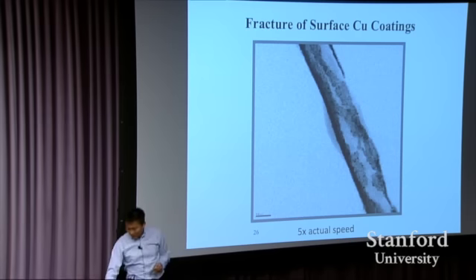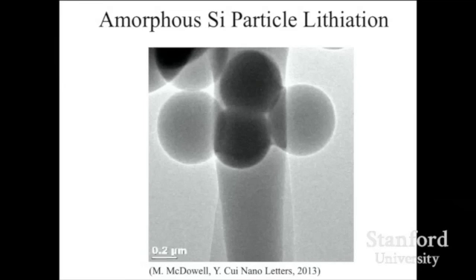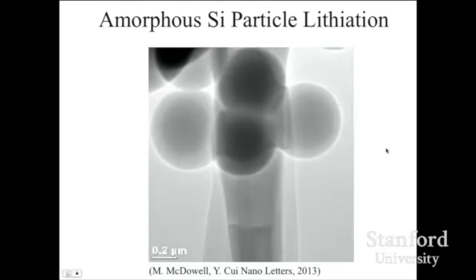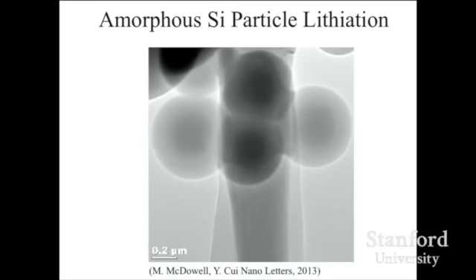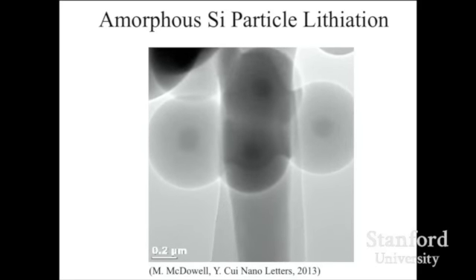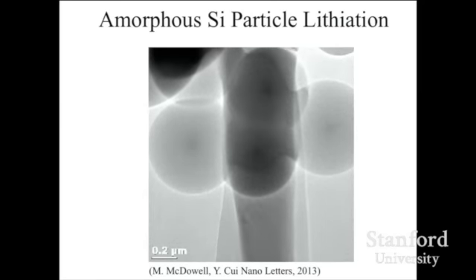They're small enough. And this is another structure using amorphous silicon particle. It turned out not only crystalline silicon can store lithium, amorphous can store lithium as well. If you look at how lithium comes into amorphous silicon, this is amorphous particle. You see this crystalline silicon nanowire get lithiated, and there's a phase boundary right there. Using this type of tool, we started to understand what's happening in these battery materials. This is very, very cool. It's only in the last couple of years in the material science community that a tool like this was used for the first time to really try to understand what's happening inside the batteries.